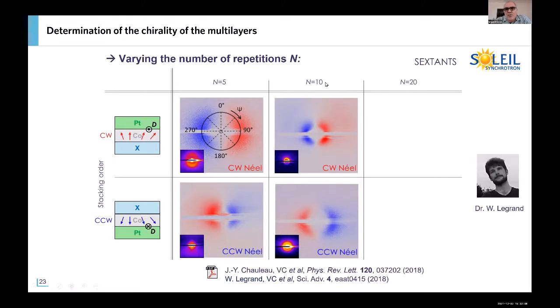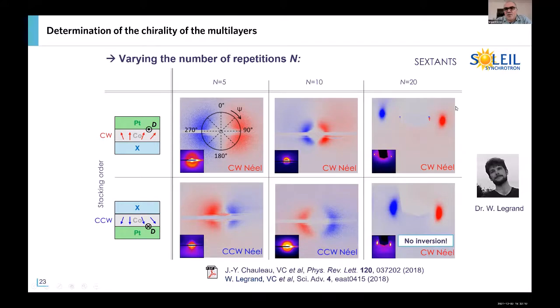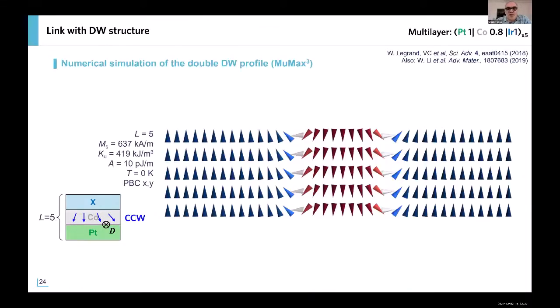When we repeat the same with 10 repetitions, we have exactly the same results. But then the surprise was for 20 repetitions, we find that there is no inversion of the dichroism when we change the stacking order. And the reason for that is that in this multi-layer, if you have a large DMI and a small number of repetitions, in this case 5 repetitions, we calculate using micromagnetic simulation that we have basically the same configuration in every layer, and these are skyrmions with chirality defined by the DMI.